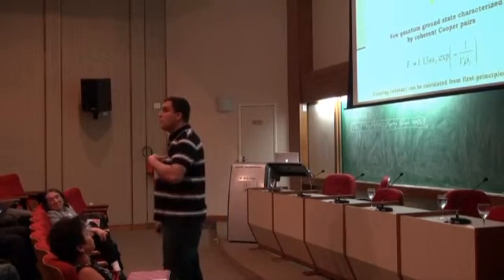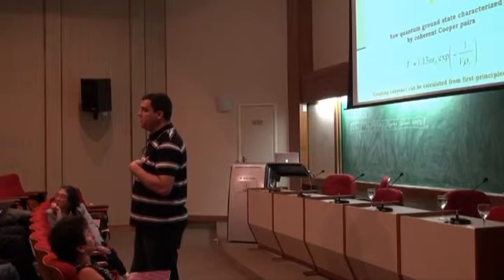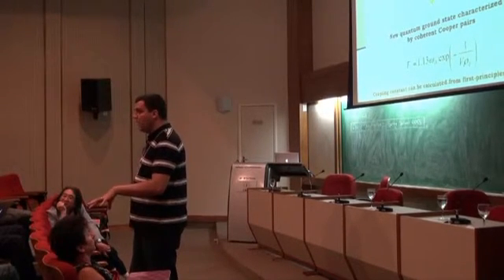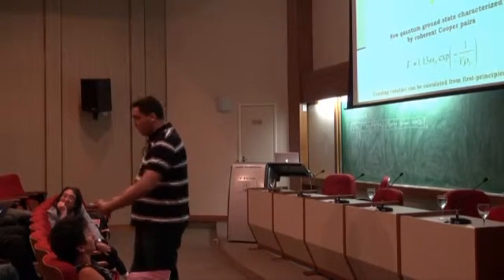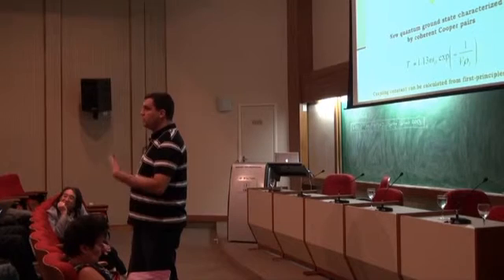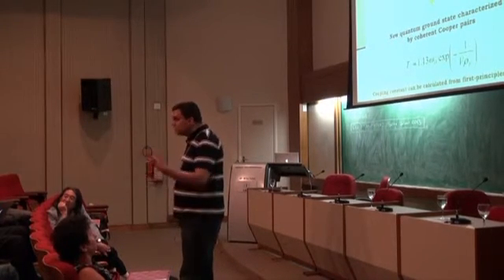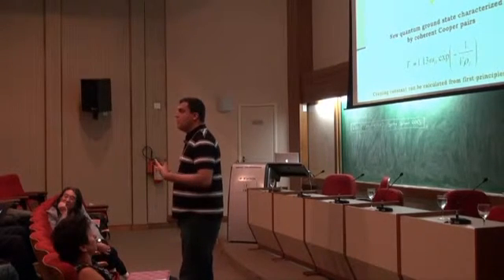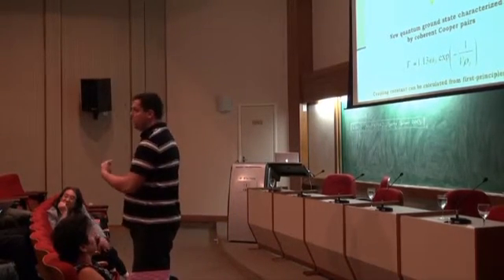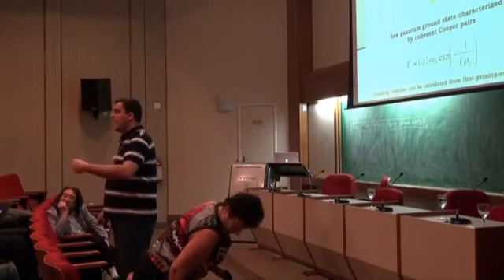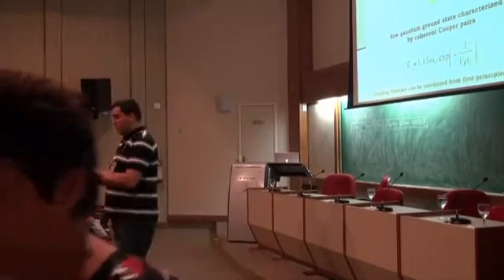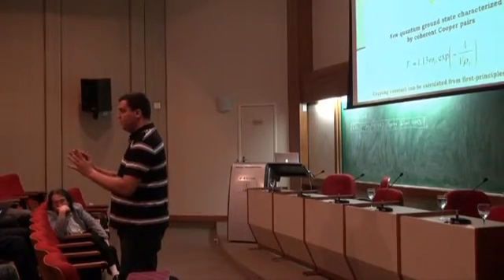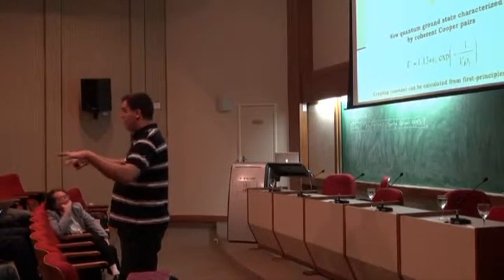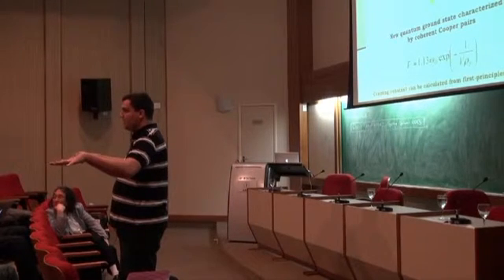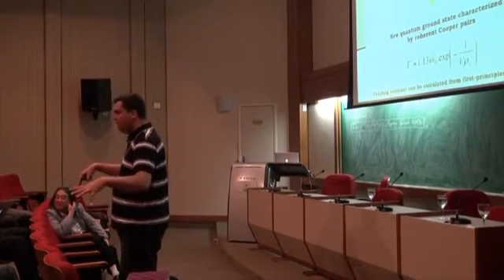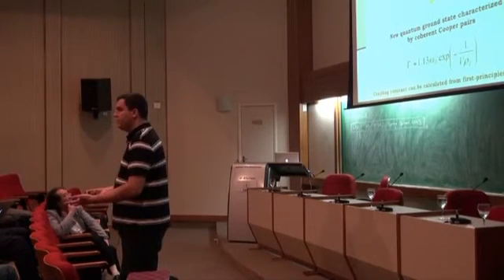What seems, from my perspective, and that's a very biased perspective, very promising, is that I actually just take DFT and the modifications there to include pairing and the possibility of pairing. This has been done by groups at the University of Tokyo, actually, and they get much closer to a good prediction of Tc. I personally think that doing a consistent LDA version, because LDA is just a way of calculating the functional based on the uniform electron gas, we need an equivalent of LDA for superconductivity, and you can just do DFT.